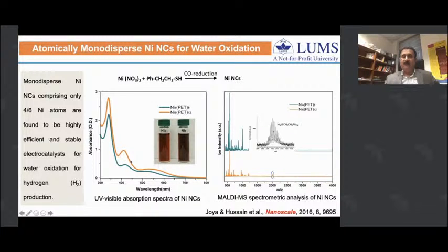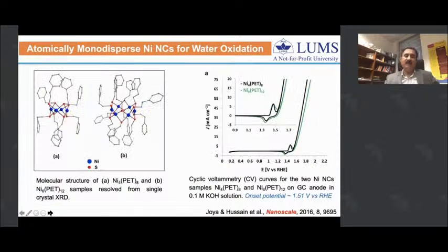The optical absorption here is not due to surface plasmon resonance, as you would normally see for gold or silver particles, but due to HOMO-LUMO optical transitions, because they behave almost like metal molecules. They're so small that it's really difficult to characterize them using even high resolution transmission electron microscopy, so we need to use MALDI mass spectrometric techniques.